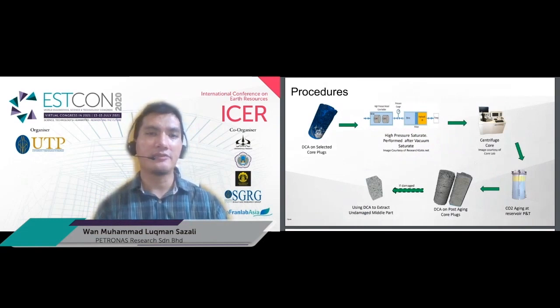Here are the procedures of determining geochemical reaction with the help of DCA. First, the selected sample was scanned under micro CT scan to produce a high resolution 3D image. Next, the selected sample was saturated with synthetic brine based on X-field formation water. Next, to mimic the condition of the gas-bearing zone, the saturated samples underwent centrifuge until only irreducible water saturation is left in the sample. Next, the samples were aged in a batch reactor with CO2 at reservoir pressure and temperature. After aging, the samples were scanned once again under micro CT scan to produce a post-aging image for DCA analysis.